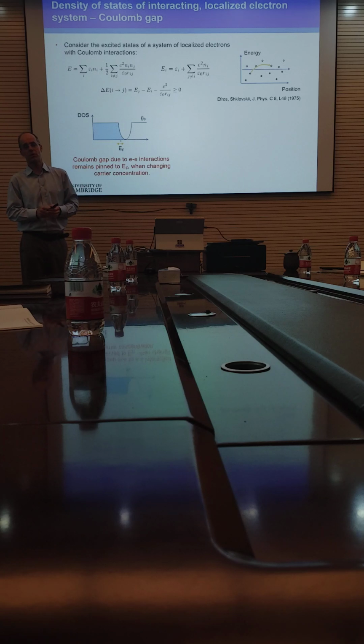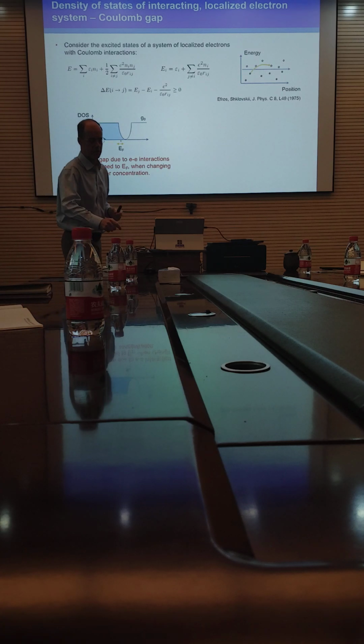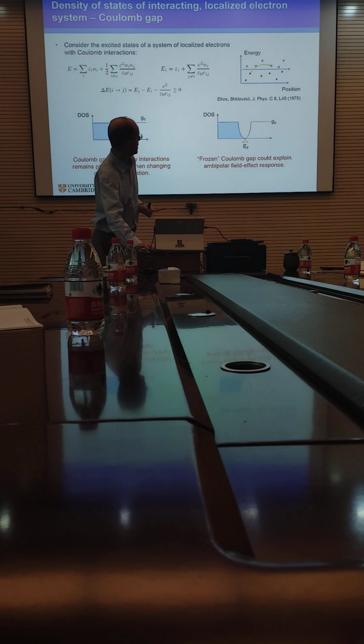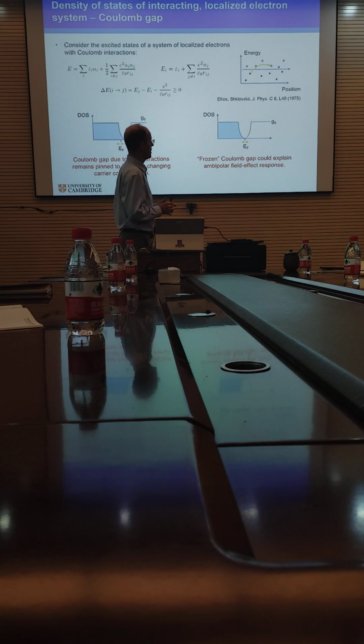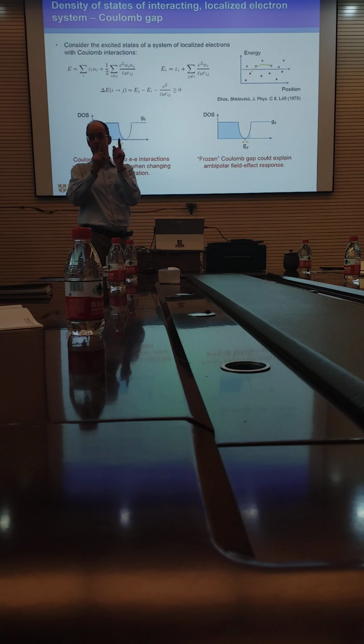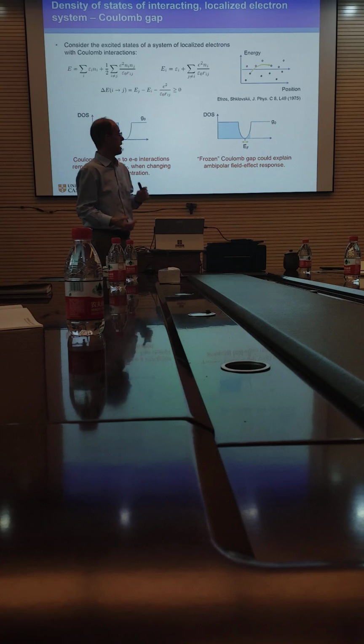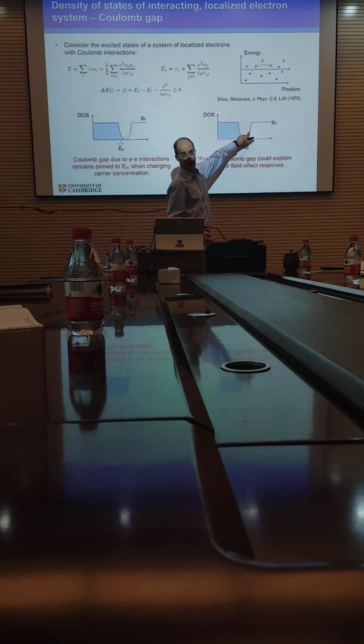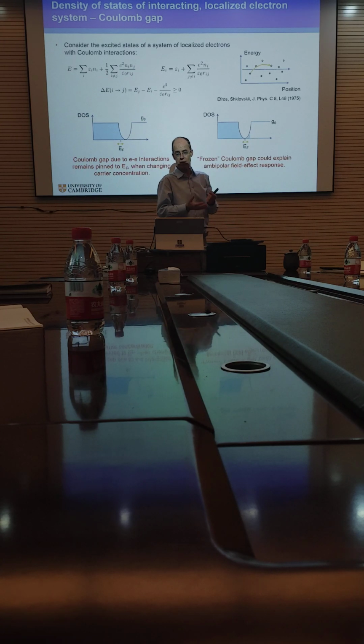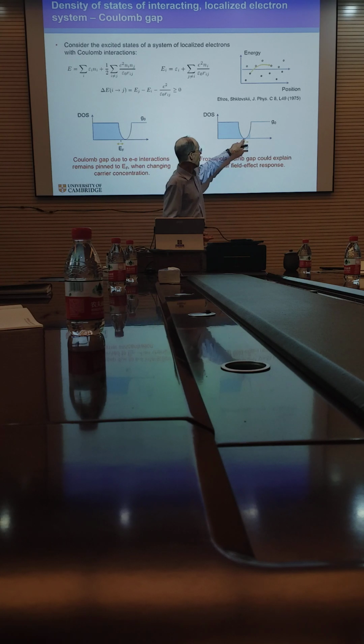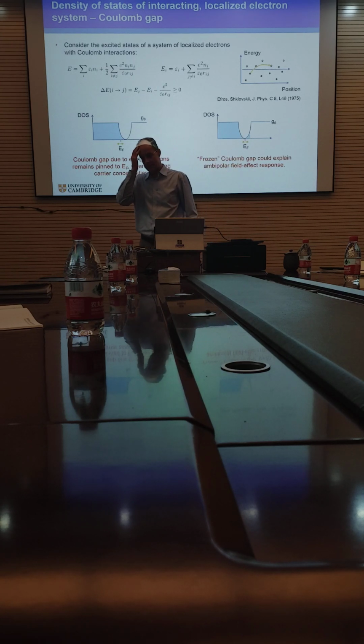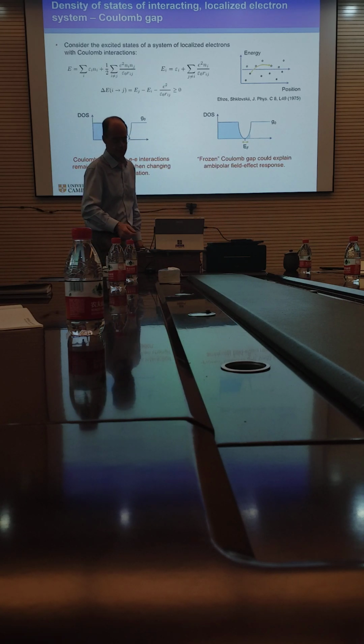What we would need in order to explain our results would be something like a frozen Coulomb gap, where as you add extra charges in, maybe you can actually move the Fermi energy out of the center of the gap to the sides of that gap. And then you could access states with higher density of states, and that could explain why we see this increase in conductivity as we add more charges and/or take some charges out. So that was the idea. Can we come up with a mechanism for freezing this Coulomb gap?